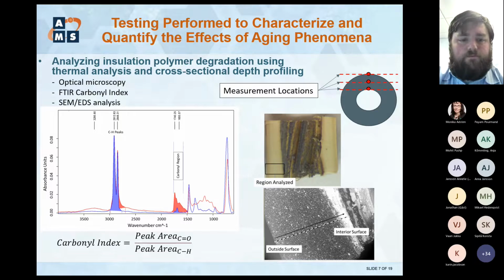The data on the left just shows how we do the carbonyl calculations. We take the peak area of the CH peaks, with the peak max around 2,900, 2848 wave numbers, and then we integrate that, take the area of those peaks, and use it to normalize the carbonyl region, which is around 1750 down to a little less than 1800, which you see in the plot there. The blue in this case is baseline data. The red represents an aged sample, and you can see the differences in the peak amplitudes and the peak areas. And that's how we define it, taking the ratio of the carbonyl peak area to the CH peak area.